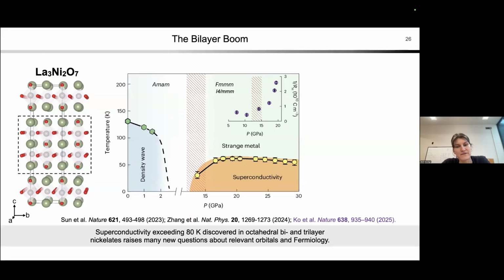And the first discovery of superconductivity was in bulk crystals, again, at very high pressures. So not as high, like 100 GPa, but still 20 GPa, which is nothing to sneeze at. And from X-ray measurements, it was noticed early on that the onset of superconductivity seemed to correlate with an onset or a change in the crystalline symmetry. And so this again goes back to this idea of very close coupling between the lattice structure, the electronic structure, and the functional properties of these materials.